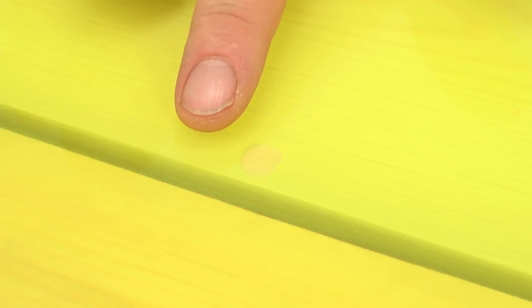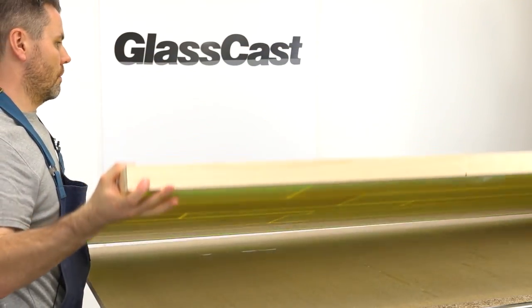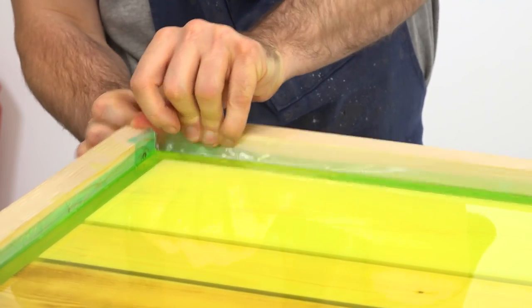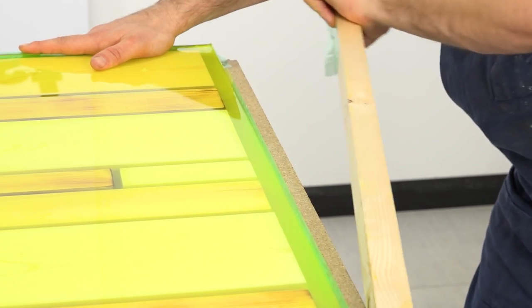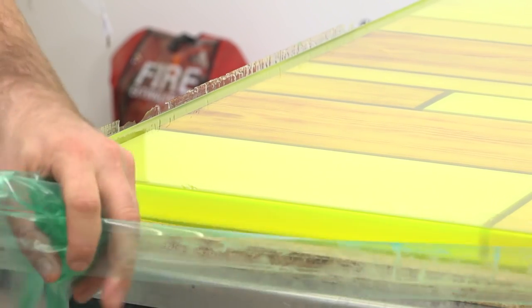There are a couple of air bubbles visible where maybe I needed to be a bit more careful to lower the planks into the resin on an angle, but all in all, this looks very smart for the underside of the table. As you can see, it's easy to separate the barriers away from the cured resin, and the release tape that we've used actually leaves a pretty good finish right from the off. The next step is to tidy up the edges.